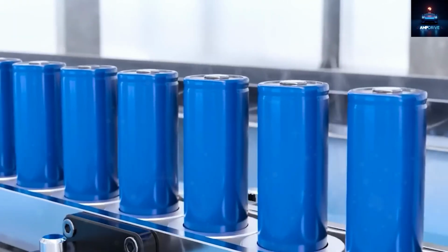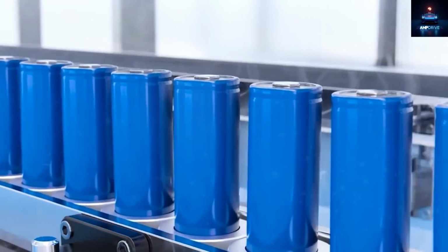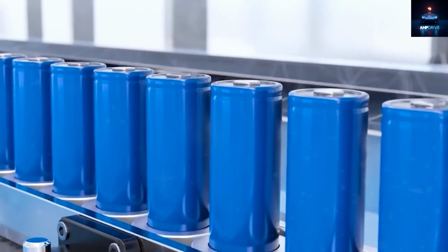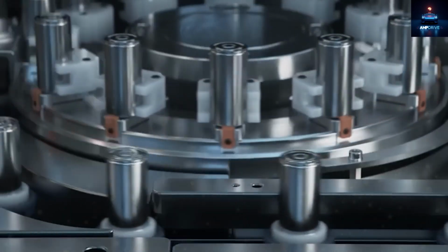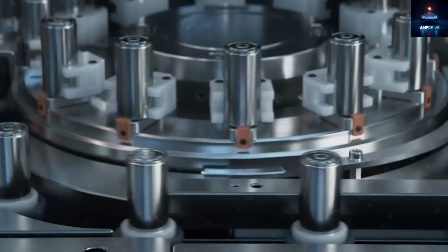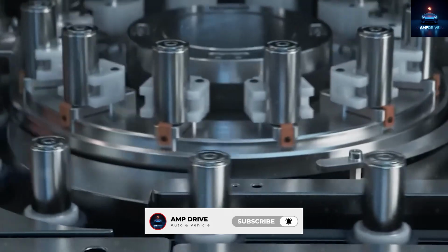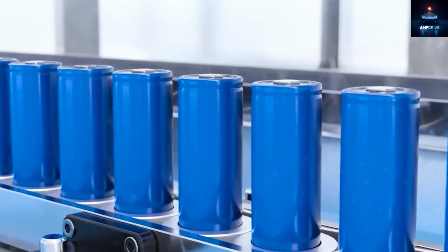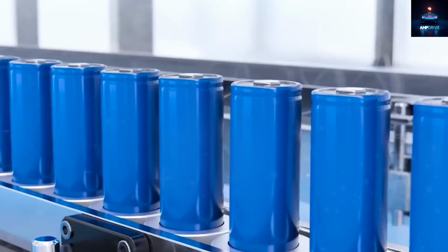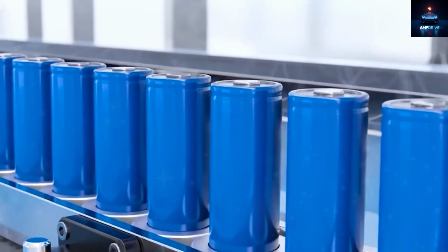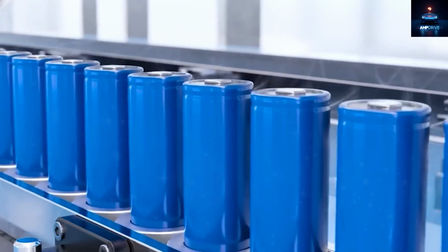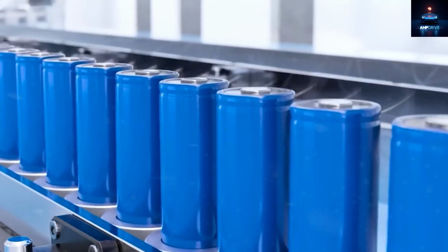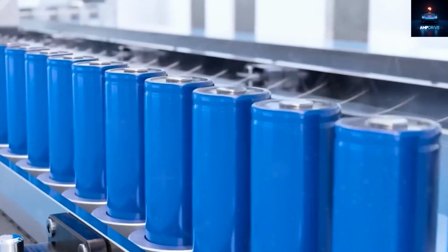With a current energy density of about 60 watt-hours per kilogram, just a quarter of Tesla's 4680 cells and far below the 500+ watt-hours per kilogram promised by CATL's lithium-metal chemistry, a polymer pack for a 300-mile mid-size crossover would weigh over a ton and eat up cabin space. Add a high self-discharge rate, several times that of lithium-ion cells, and the case weakens, as a car losing charge while parked could become a customer headache.